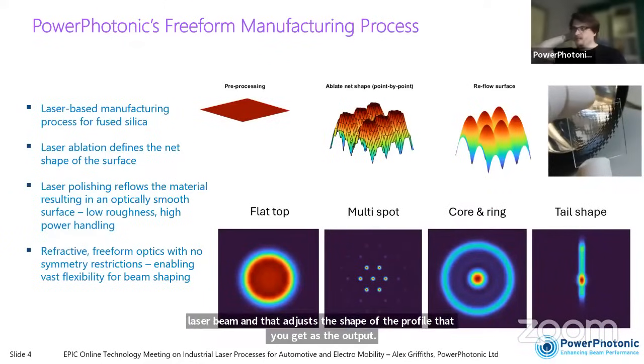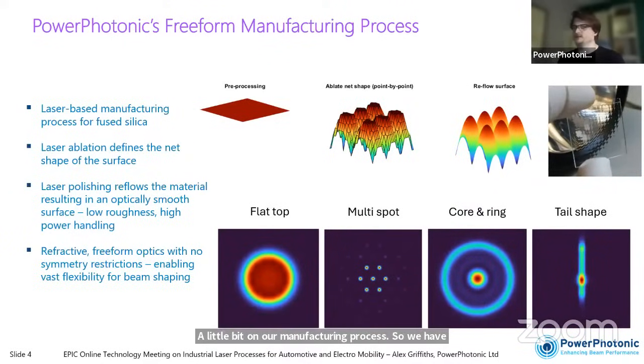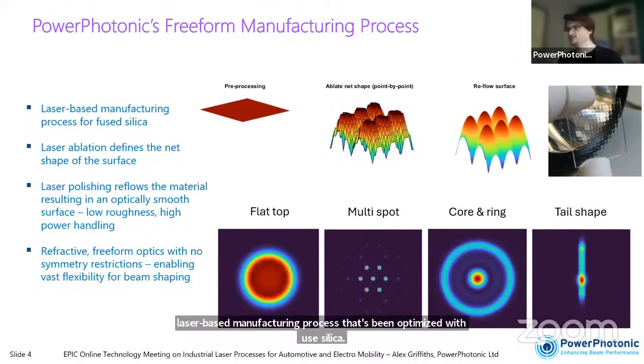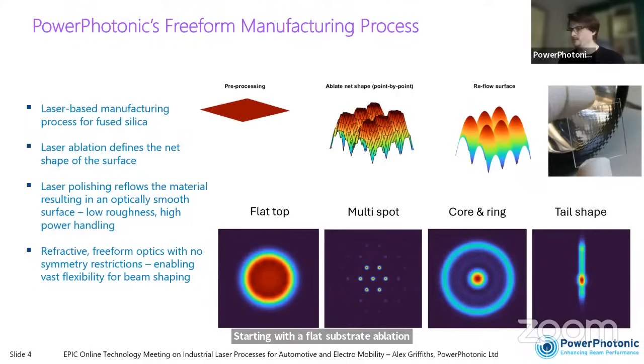A little bit on our manufacturing process. So we have a laser-based manufacturing process that's been optimized for fused silica. Starting with a flat substrate, ablation produces the large-scale structure of your optic in a point-by-point manner. And then afterwards, the surface is laser polished. This reflows the surface and produces an optically smooth finish. This means we retain the bulk properties of fused silica. We have high power handling and low surface roughness, which means low scatter.